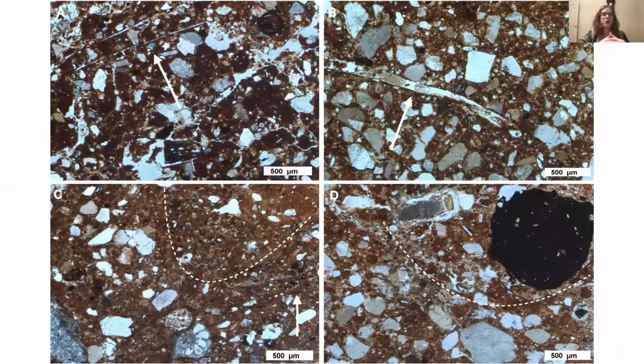And finally, we could distinguish two microfabrics, a fine fabric which seems to indicate that the raw material was actually screened before the manufacturing, before the mixing of the elements happened. Simply put, the big inclusions were removed and the soil was possibly even sieved before the actual manufacturing. But we also could identify a coarse fabric that shows fewer traces of pugging and kneading and presents sort of a clear separation between fine and coarse fraction. Both features, though, seem to indicate that this coarse fabric was linked to a hastier manufacturing event.